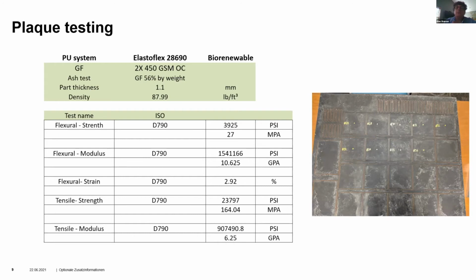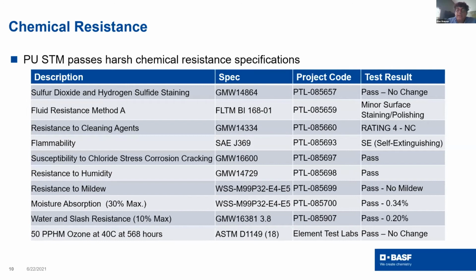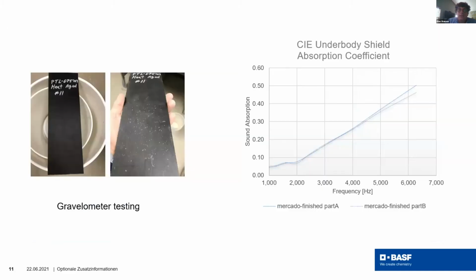So first of all, we were successful to make such a sheet, which is like out of 450 gram per square meter of glass fiber. Not only we did the mechanical performance, we took all the specs that OEM provides, and we did the chemical resistance for it. Those are like the GM and the Ford and some of the foreign automotive specs that we all passed based on that. That means when we passed, that means all the specs passed the requirement. We did also, like, throwing like gravelometer testing and also NVH testing. All of this is under the compliance of the specs that we received from the OEMs.